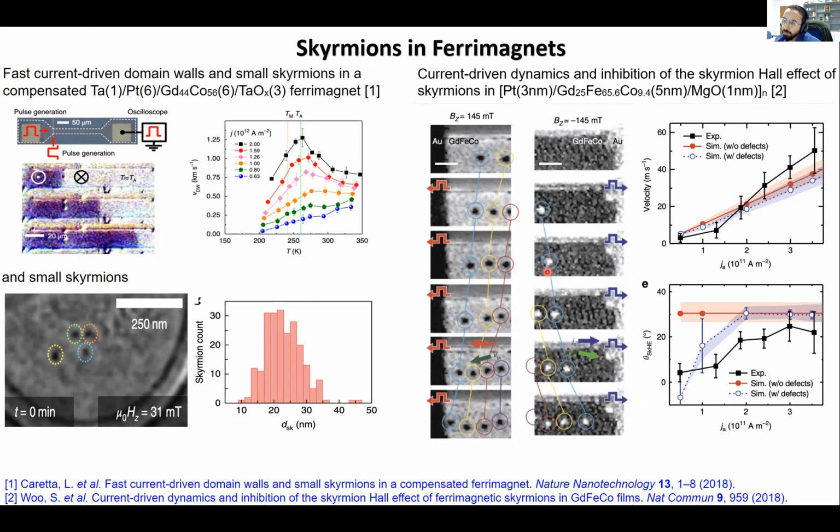However, unlike the 2017 publication in ferromagnetic materials, where you could generate a lattice of skyrmions, in these ferrimagnetic materials you can only generate individual skyrmions, which was the case earlier when we started with ferromagnetic materials. So even in ferrimagnetic materials, we are in a phase now where we are only able to generate individual skyrmions. But to really go ahead, we need to generate them in bulk and at very high densities, in a lattice formation.